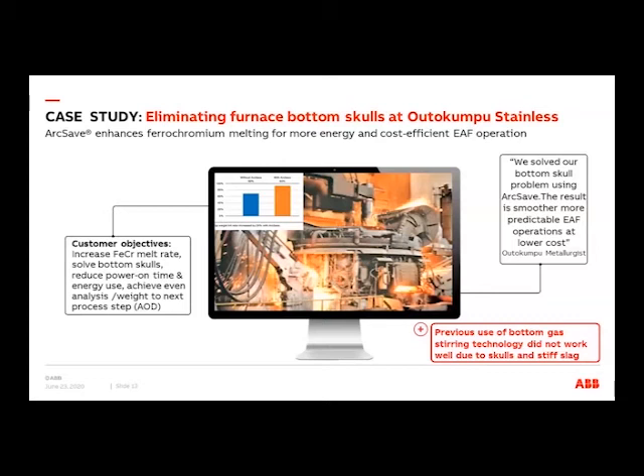They also wanted to reduce the power-on time and energy, and not the least, also achieve even analyses, temperature and weight to the next process step, which was in this case the AOD converter. They also used to have bottom gas stirring porous plugs, but these were routinely clogged around 100 to 150 heats, and therefore they couldn't use them due to the bottom skull problem and the very stiff slag. One quote from one of the metallurgists at Outokumpu was, "We solved our bottom skull problem using the ArcSave. The result is smoother, more predictable electric arc furnace operation at a lower cost."